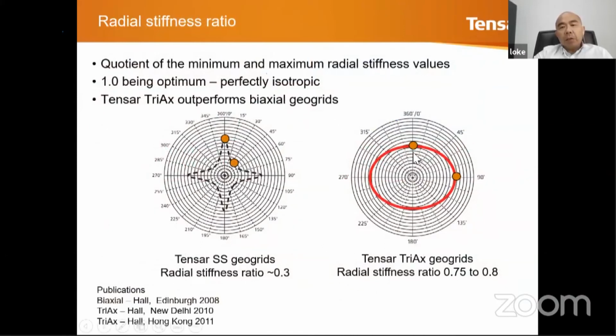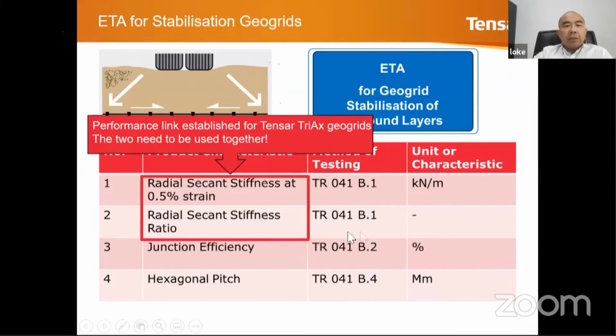But stabilization is what we look at. We look at radial stiffness. We look at radial stiffness ratio. In other words, the stiffness in different directions is more or less the same. And the radial stiffness ratio, which is the ratio between the lowest stiffness and the highest stiffness, is close to 1. So in stabilization, these are the two parameters that we are looking at. You cannot separate both of them. These come together. These are performance parameters linked to establish the geogrid performance.